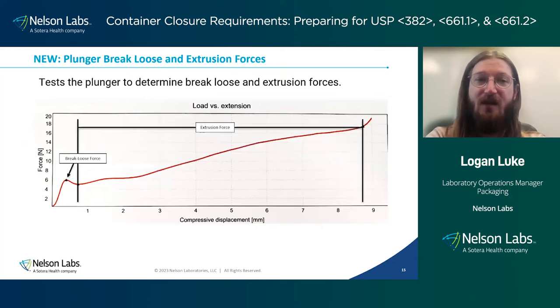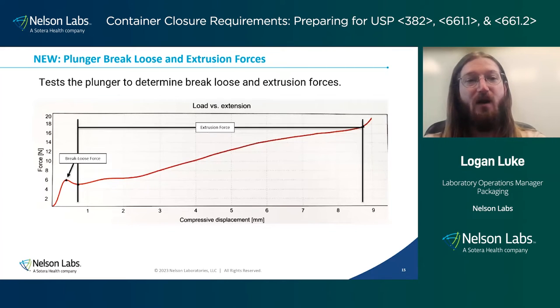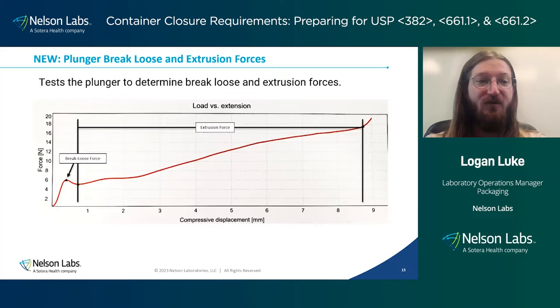The next new test that we have to look at is break loose and extrusion forces. The break loose force is sometimes called the initiating force. And if you look at this graph here, that first peak that I have pointed out is called the break loose force. This is followed by measuring the plunger extrusion force. Sometimes you can hear that force called the sustaining force or the glide force. This is the force that's required to sustain the plunger to expel the contents of the syringe. Ultimately, this test is demonstrating the ease of product delivery.